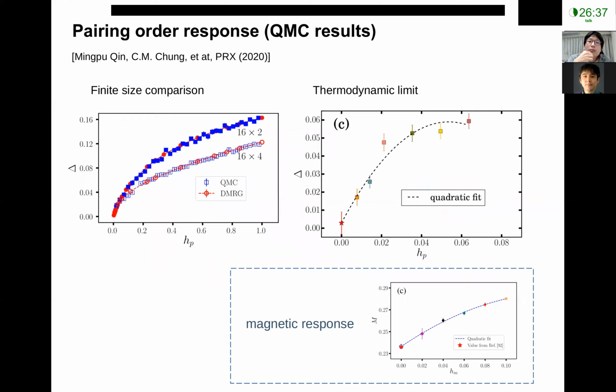Then we use the other approach, which basically tells us the same story. In this case, because we already know the pairing symmetry, we apply the D-wave pairing field globally on the system to induce the pairing order, as shown here, where HP is the magnitude of the pairing field.